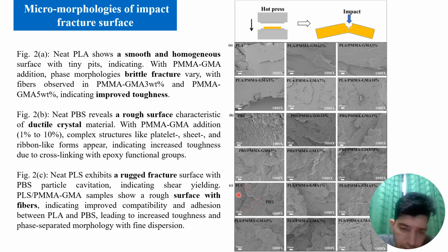After that, PLS. In PLS, it is the combination of PBS and PLA. Some PBS particle cavitation was observed here, which can easily show the shear yielding. By adding 1%, 3%, and so on of the compatibilizer, the surface becomes more rough. Here it is a little bit similar to this one, not too much, so it fractures easily as compared to this one. This rough surface shows the compatibility is increased, which can improve toughness, and it also shows a fine dispersion, phase separated morphology. It's observed here.